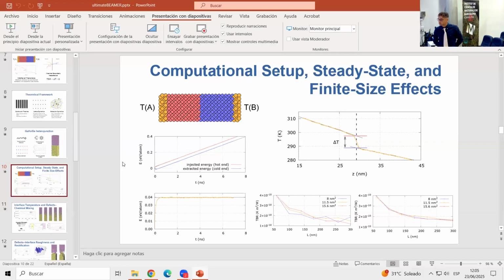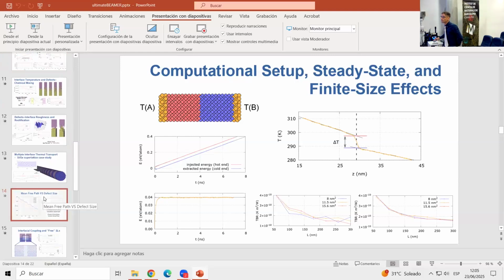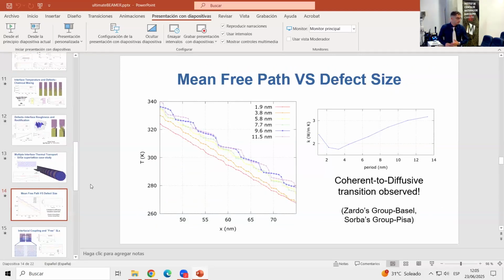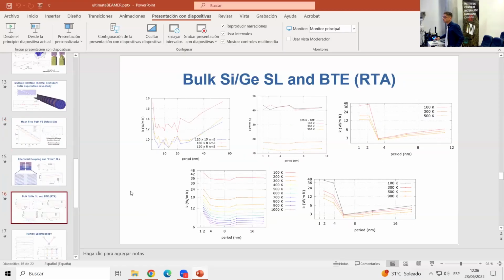So I had another question about the other main result, which is the transition from coherence to a diffusive behavior. It's very nice that you can correlate this linear temperature profile with the coherent regime. And in MD, in principle, you are modeling full physics simulations, in the sense that you have both incoherent and coherent mechanisms. So to me, it's very natural that you can observe this in MD. But the BTE is a particle-like description of phonons, meaning that you are modeling the phonon gas distribution function. They have a well-defined velocity that you can relate with the dispersion, basically a group velocity and a scattering probability. So I was surprised to see that in the BTE you also recover a minima. My question is, what boundary conditions are you using to reproduce such a minima?